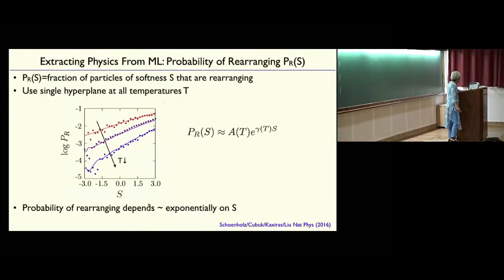Now here's the important thing. If I look at the probability that a particle of softness S is going to rearrange, what we see is a roughly exponential dependence on softness, and the prefactor in that exponential depends on temperature. It's not so great at high temperatures, but as we go to lower and lower temperatures, it's a stronger and stronger function of the softness. The probability of rearranging is monotonic in softness: it's low for a very negative softness and much, much bigger for a positive softness. So what we're looking for is a steep dependence on softness.